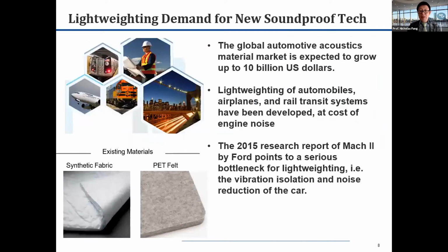And a very important attribute of such lightweight substrates and materials is found in the transportation space. In the previous talk, we heard that we can use some fiberglass absorbers, for example, in support of the conformal antenna design. But in the acoustic domain, there will also be very similar needs. And in this case, we are looking at shells or enclosures that are thinner and lighter weight, for example, to bring fuel efficiency higher. Unfortunately, in this case, we are seeing a similar limit of the material thickness versus the acoustic absorption or soundproof efficiency.